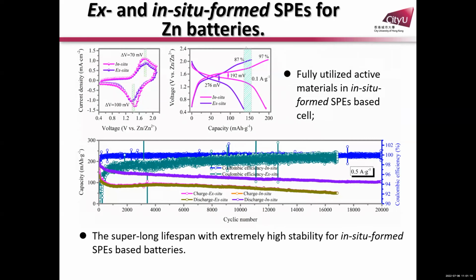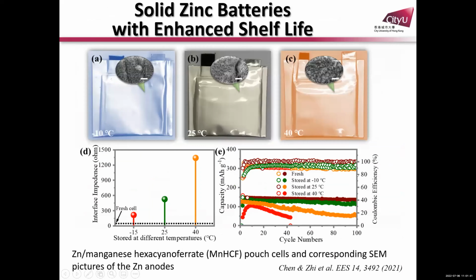This is for batteries with these polymer electrolytes that we can use. We can only use PBA as the cathode. Zinc, manganese oxide, and vanadium oxide are not very attractive in this case if you use solid state electrolyte. But stability is very good, though you sacrifice the kinetics, so rate capability is actually not good if you use solid state batteries. We're also trying to solve this problem with solid batteries.